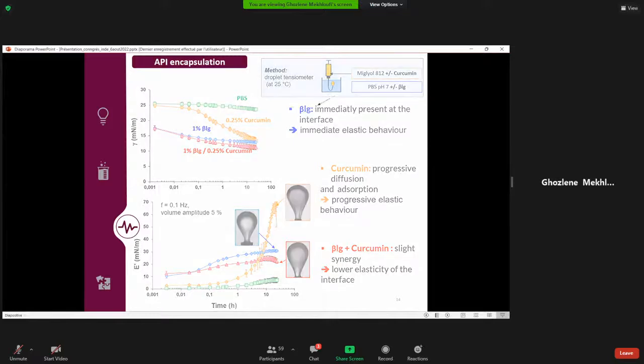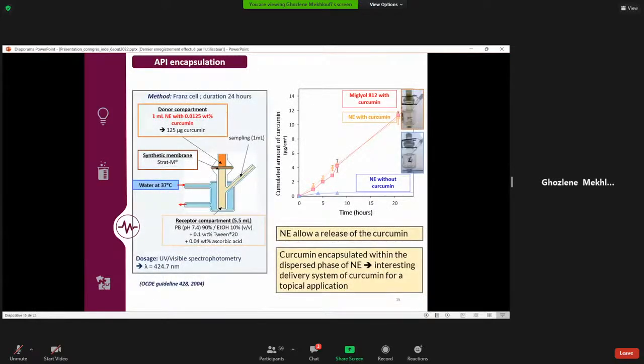After that, we aimed to determine if the encapsulated curcumin can be released from the dispersed phase of the nanoemulsion. For that, we led an in vitro diffusion study over 24 hours at 37 degrees using a Franz cell device. We put our sample in the donor compartment in contact with a synthetic membrane which mimics the skin. And we put in the receptor compartment a mix of phosphate buffer, ethanol, and surfactant, and also ascorbic acid. And after sampling in the receptor medium at different times, the curcumin concentration was determined by UV-visible spectrophotometry.